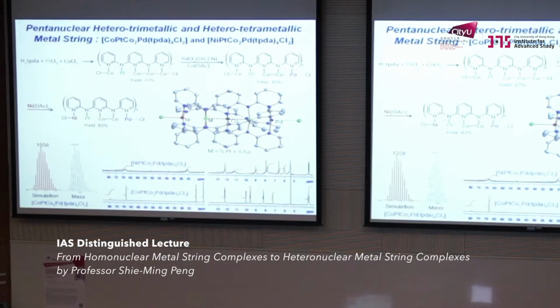The last one, I will show you the synthesis of the nickel, platinum, cobalt, palladium tetrametal string. As I mentioned, thermodynamically this nitrogen prefers the Pd metal, but because the Pd metal are inert, they are difficult to substitute. So the easiest way, even for the penta-cobalt system, by our Chinese cooking, we can get 27%, not too bad, cobalt, platinum, cobalt. This is the first step.